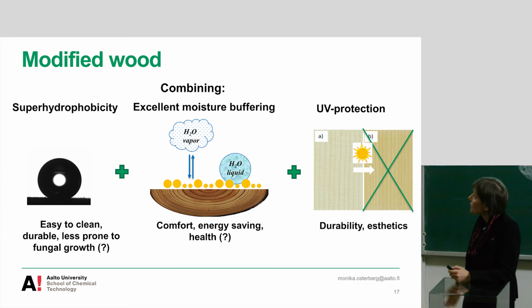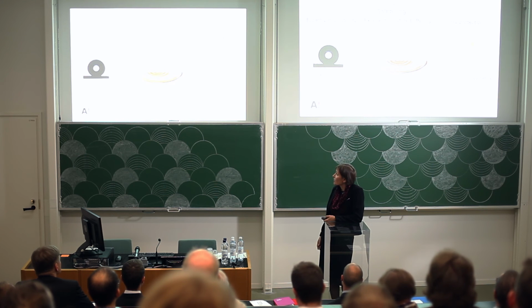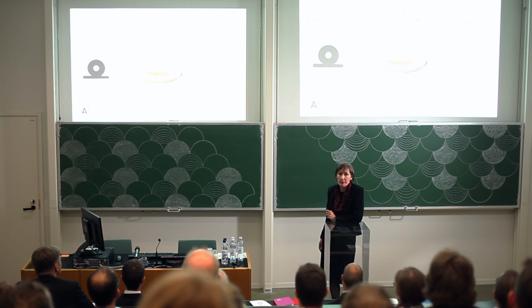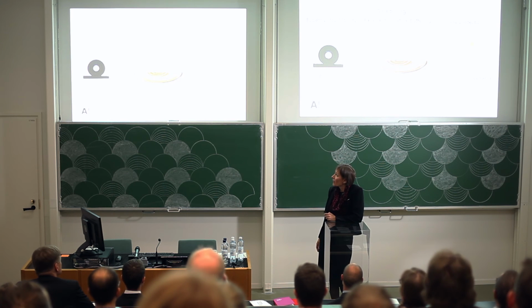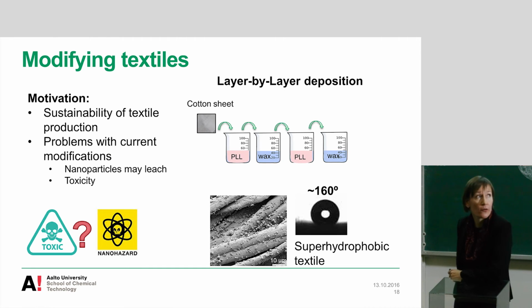So we were able to combine this super hydrophobicity, which makes the surface easy to clean, durable. I think it also makes it least prone to fungal growth because fungi need the water to grow. And then we combined this with excellent moisture buffering, which gave the comfort. And the UV protection, it wasn't great, but we got some UV protection with this modification. And we did the same for the textiles.